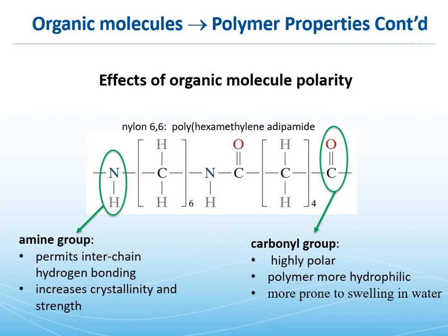So if you took two of these molecules and laid them side by side, the nitrogen-hydrogen bond, being electropositive, would want to kind of butt up against the carbonyl group, making a dipole-dipole secondary bond. And that kind of interlocking indexing, so to speak, actually allows us to crystallize very well and contributes to stronger mechanical properties, even though it's just a thermoplastic. Flip side, nothing's free, right?